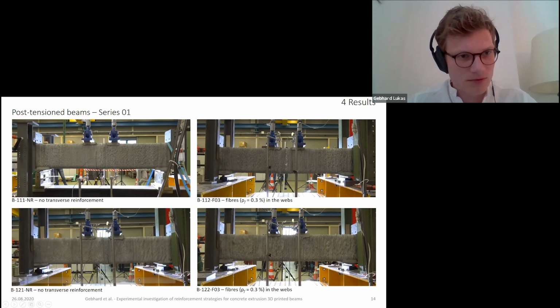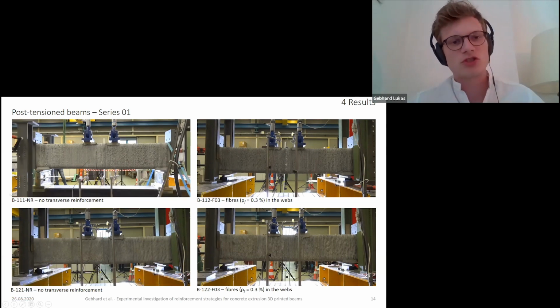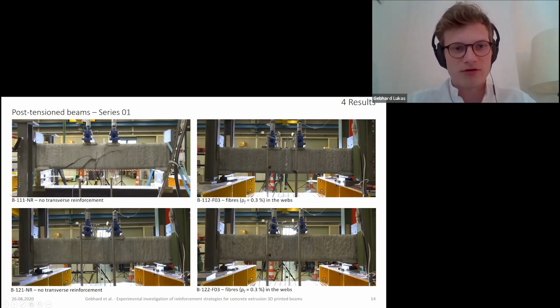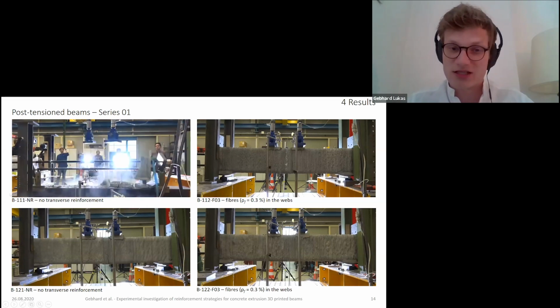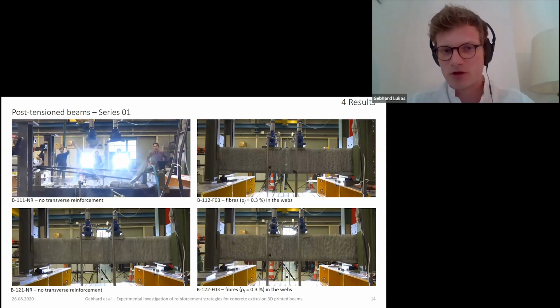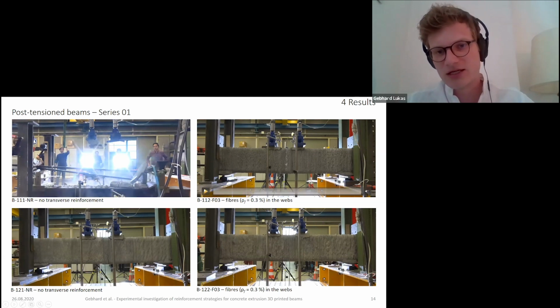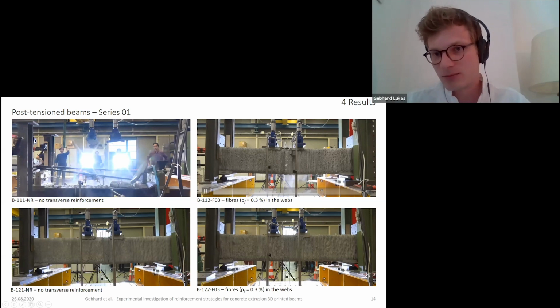So this video shows you the failure of the beam. So we see an explosive failure of the beam because we have no bond between the concrete and the reinforcement, and we also don't have any reinforcement in the concrete itself. Now, when we added the fibers, we achieved again a brittle failure of the concrete here in the compression zone, but the overall structure of the beam stayed intact, so no catastrophic failure.